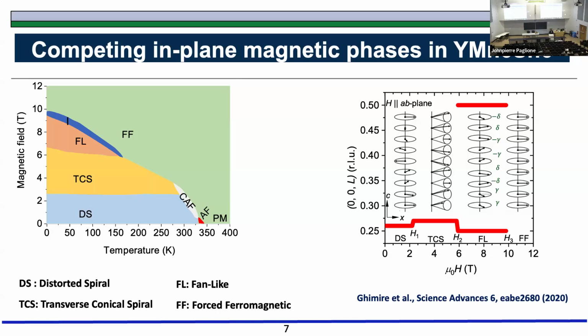And then, see, this material was synthesized. We are not the first ones to synthesize it; it was several years ago. And these magnetic properties were also known. What was not done is that the phase diagram was not mapped out. So we mapped out the phase diagram, and we found very interesting stuff. It orders at about 350 Kelvin in a simple antiferromagnetic state. And then as you lower the temperature, the antiferromagnetism distorts and starts rotating from one plane to another.